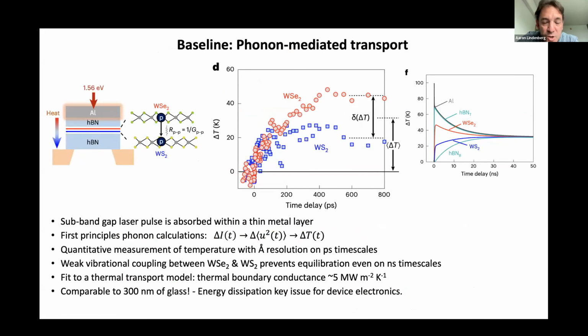Okay, so I'm going to show you two different experiments where we probe interfacial coupling in these systems. The first is a measurement where we add an additional layer. We have an additional thin aluminum layer on top of this heterostructure sample. So now the idea is we come in with an 800 nanometer pulse. All of the energy is directly absorbed in this top thin metallic layer.